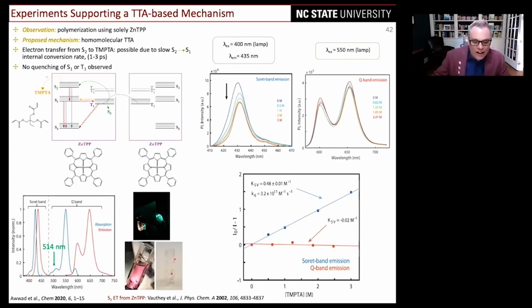And as the warning I told you, you see what happens to the cuvettes. So then you have to use Nochromix to clean them out. So I would not try to do these. It's very efficient at polymerizing. Do not do this in cuvettes if you want to not have to worry about cleaning them out.